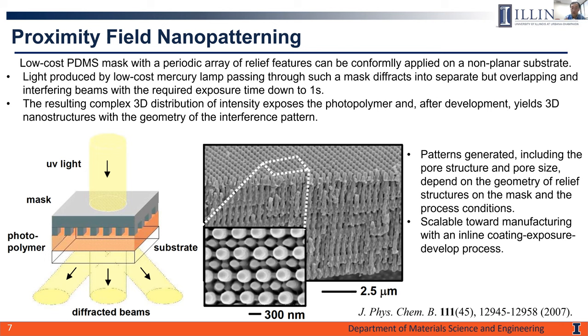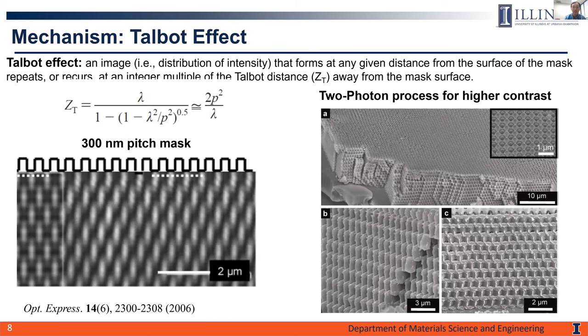It is a high throughput single exposure process to generate this regular pore structure in 3D, and the pattern generated, including the pore size and the pore structure, depends on the geometry of the relief structure on the mask and also the process conditions. Therefore they can be controlled and adjusted. The mechanism here is based on the well-known Talbot effect. The characteristic length of the 3D structure generated is the Talbot distance, and it scales with the periodicity of the phase mask as well as the wavelength of the incident light.